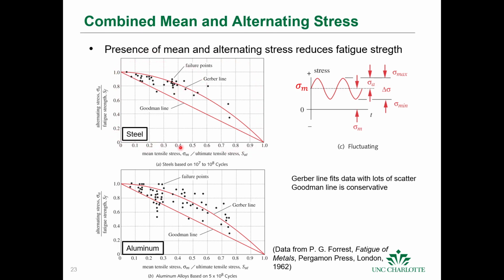Okay, and this gives us a relationship for fatigue strength when we have alternating stress and a non-zero mean stress, and it's normalized by the ultimate tensile stress. So that's how we construct this graph. The Gerber line is more accurate because it fits the data better. The Goodman line is more limiting, and is often used for design. And so what we want is to be somewhere in this region here, where we keep our mean and alternating stresses below the Goodman line. Okay, and we'll talk about how we calculate those later.